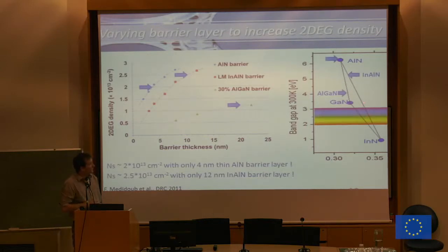Also, briefly discussed yesterday is that you have various possibilities for this barrier material. Typically, you go from GaN a little bit up to AlGaN. You can also do pure aluminum nitride, or you can do indium aluminum nitride that is lattice matched to the gallium nitride on top. And if you plot these materials as a function of thickness, you can see that for instance, with a very thin aluminum nitride barrier, you get values up to 2 times 10 to the 13th, which is about double compared to the standard AlGaN situation. And with the indium aluminum nitride, you have the possibility to go a little bit thicker. You can have even higher values, which gives you tuning parameters to play with.